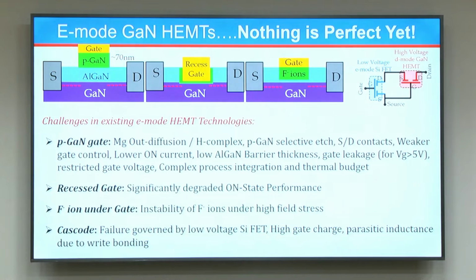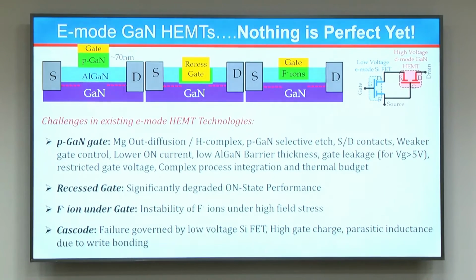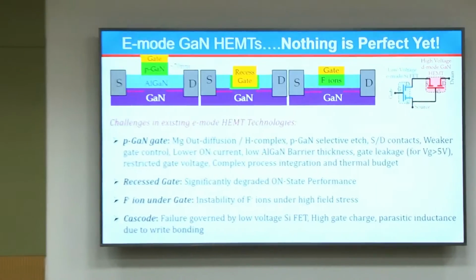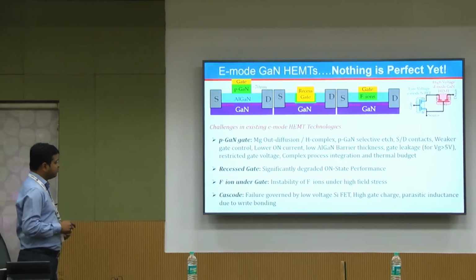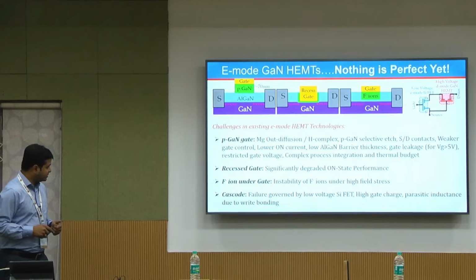I'll elaborate on this a little bit after a few slides, but let's talk about the other options that we have. Recess gate is one option, but that significantly degrades the on-state performance, and the performance is a strong function of the quality of the recess that you make. Since the recess quality could be anything, the reliability in this case also becomes a strong function of the recess that you make. The third option is you can do certain p-type implants, in this case fluorine ion implants under gate, but after a lot of work it was figured out that fluorine ions are not very stable, particularly under high temperature or high field stress scenarios, and therefore you cannot practically use these devices for power electronic systems.